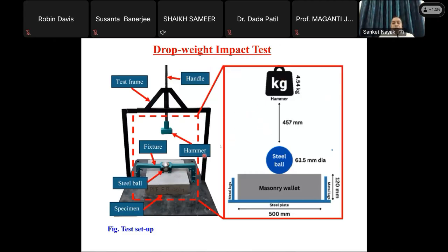So we have developed a drop weight impact test setup, and here it is a steel ball. The dimension is 63.5 millimeter diameter. Then the masonry wallet is placed. We call it a masonry wallet because the dimension is about 500 mm, and it is 1 brick thick. Height is also 500, so it is a 500 by 500 square, and the width is only 1 brick thick. The hammer weight is around 4.5 kg. The hammer is dropped from a height of 457 millimeter.